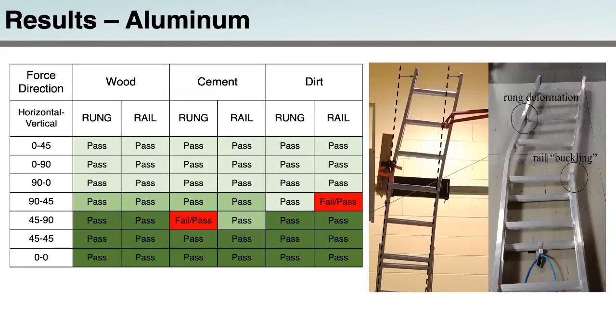Specifically, all tests in the 45 and 90 degree, so this would be the 45-degree angle and the directly rightward horizontal force directions, they produce significant ladder deformation above the tie-off location. So the upper portion of the ladder deformed in the direction of the pull force consistently, and when the deformation was inspected after each trial, 2 separate testing conditions produced failures in the aluminum ladder.